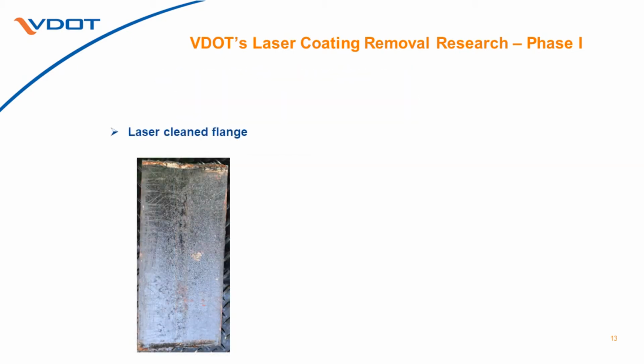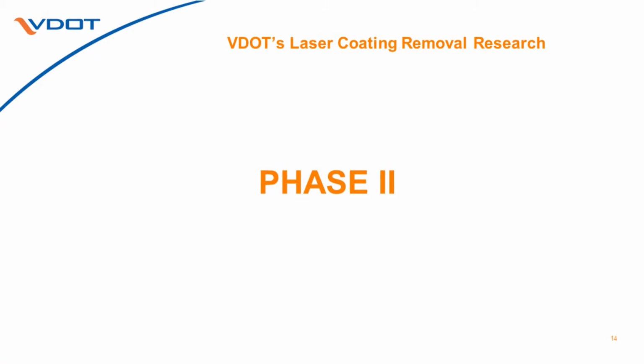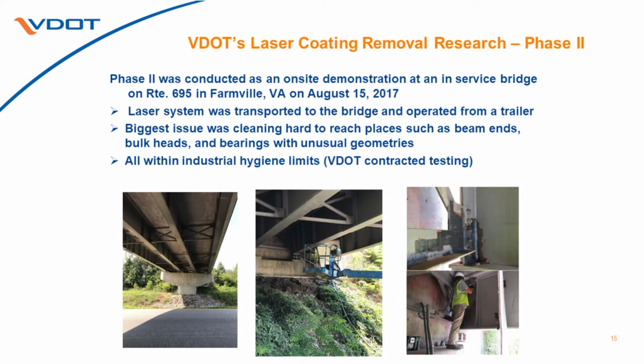This is a picture of a flange after the laser removal process has been used. You can see it's a pretty bright, shiny finish that we have there. It doesn't leave a profile, which may be, in some people's eyes, a problem, but we have discovered a paint system we can use that doesn't require a profile. It's an epoxy mastic paint, so we could use the laser without a profile and use this epoxy mastic paint as the new coating.